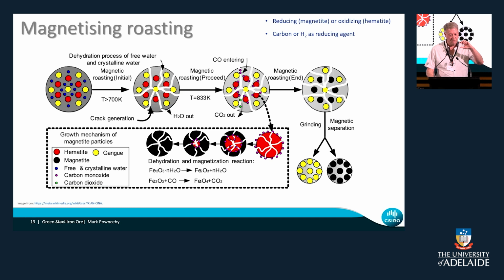It works really well if you've got discrete phases that are in there, so discrete gangue phases that will separate, and then you do your roasting, as I said, whether it's under oxidising or reducing conditions, you do a bit of grinding, and then you do a magnetic separation. And you can certainly upgrade iron ores that way.